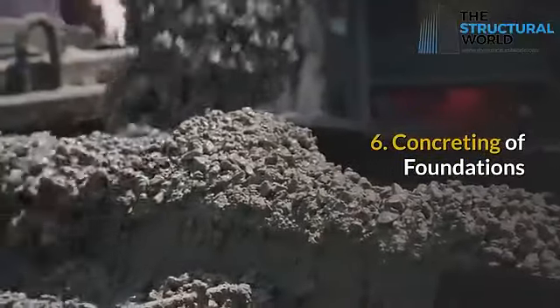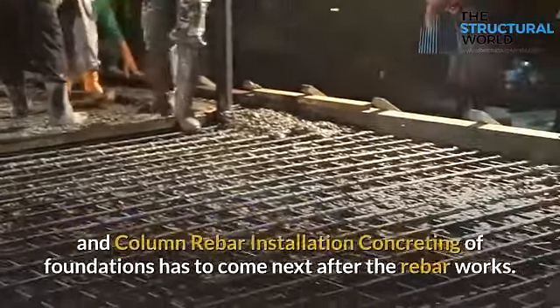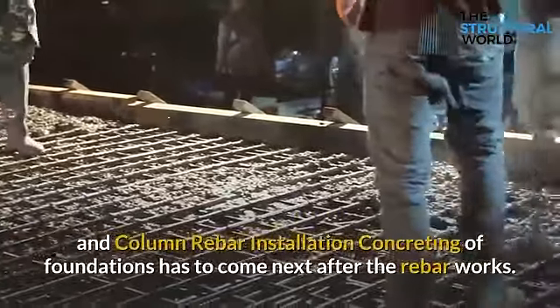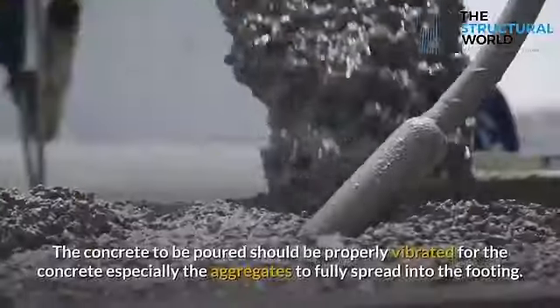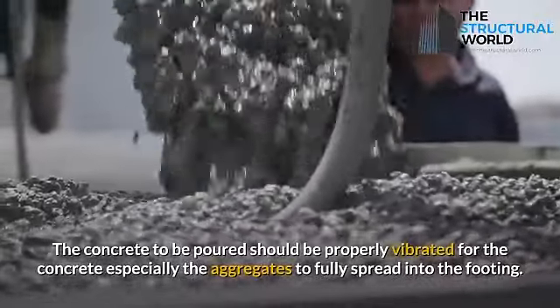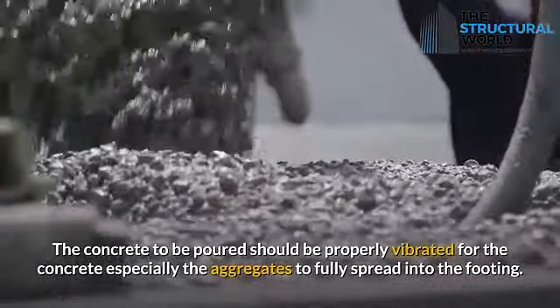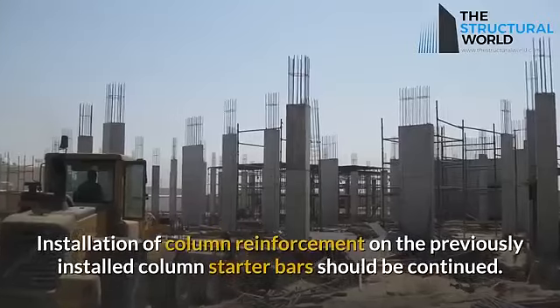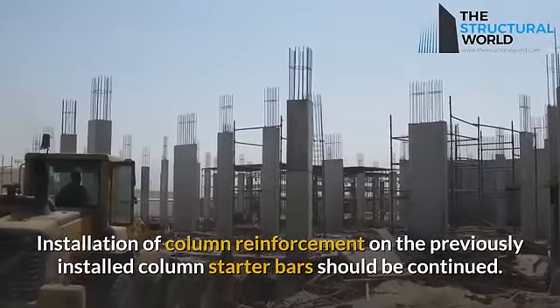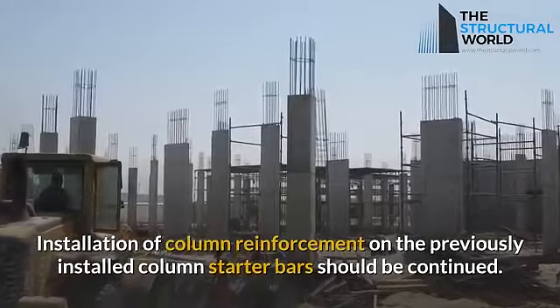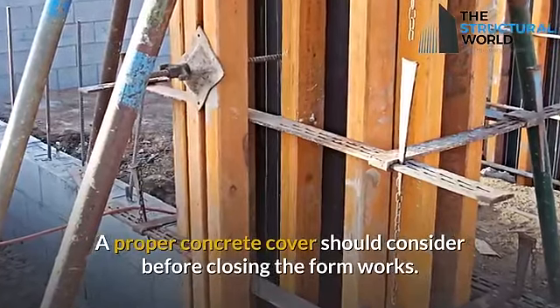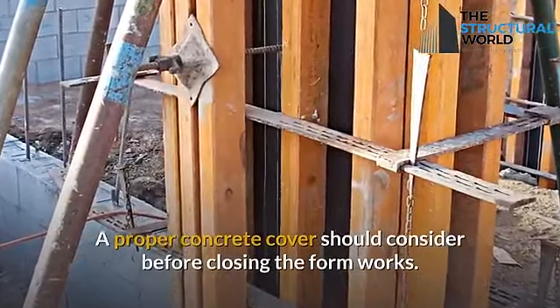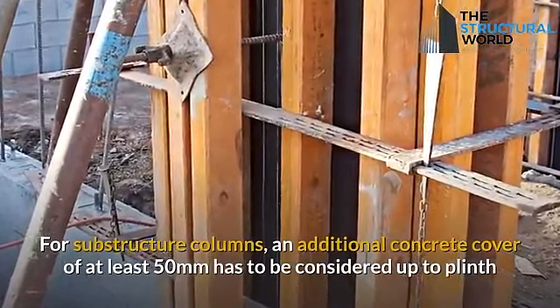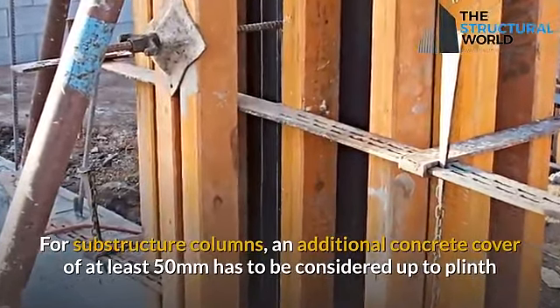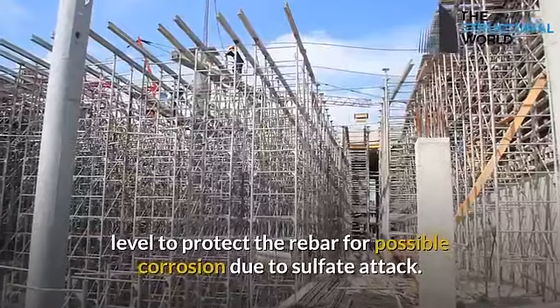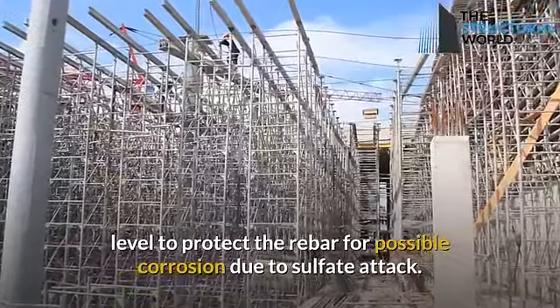6. Concreting of foundations and column rebar installation. Concreting of foundations comes next after the rebar works. The concrete to be poured should be properly vibrated for the concrete, especially the aggregates, to fully spread into the footing. Installation of column reinforcement on the previously installed column starter bars should be continued. A proper concrete cover should be considered before closing the formworks. For substructure columns, an additional concrete cover of at least 50 mm has to be considered up to plinth level to protect the rebar from possible corrosion due to sulfate attack.